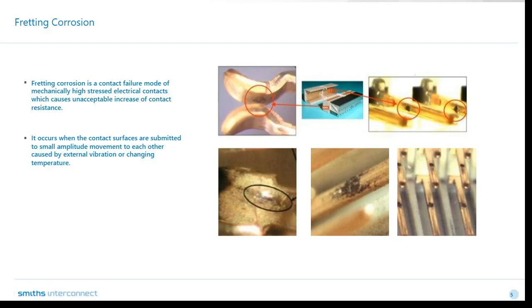An integral part of electrical connectors are the contacts within them that make electrical connections between two systems. The contacts typically have a male pin or blade and a female receptacle. Most electrical contacts are plated with gold and have an electrolytic nickel plating underneath them that acts as a barrier between the substrate and the gold. The gold is inert to oxidation, but is soft in nature and prone to wear. When the contacts are subject to micromotions and the gold is worn away, the nickel is exposed, which creates non-conductive oxide layers. As the micromotion continues, these oxides accumulate in the valleys of the asperities.